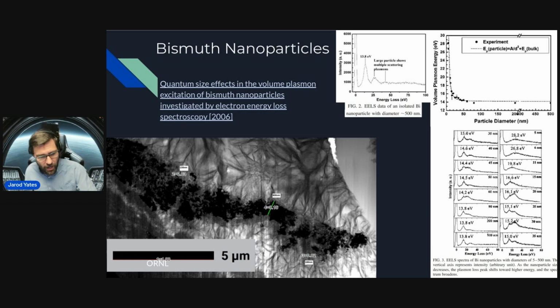So the sizes of those black dots, those bismuth dots, is somewhere in the ballpark of 100 nanometers to maybe 1,000 nanometers, a micron. And the total thickness there in the middle longer green line, that says 800 nanometers at that point. So saying that the bismuth layer is 1 to 5 microns is not accurate. In some places, it is much, much, much thinner and discontinuous, which turns out that there might actually be a use case for these things if they were discontinuous.